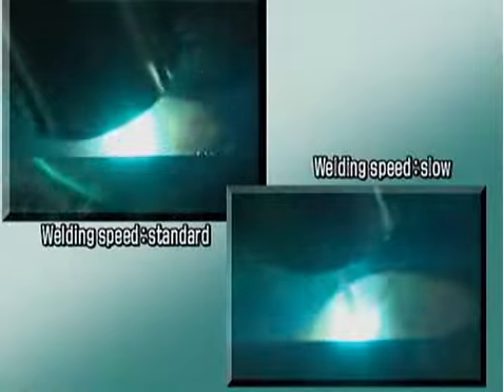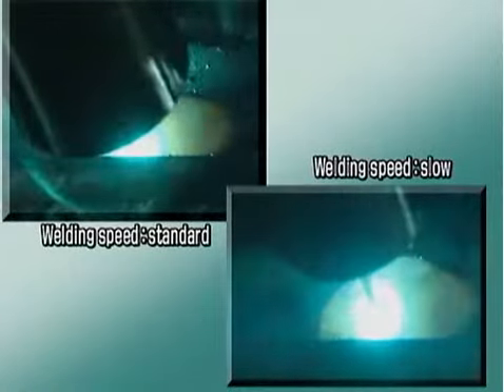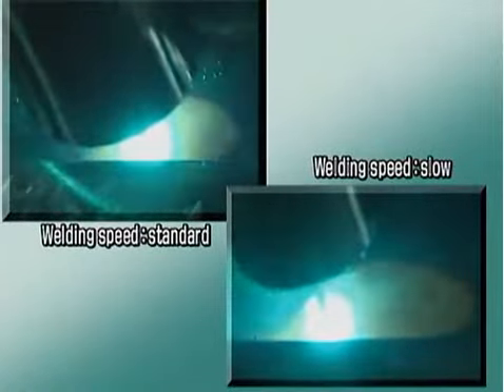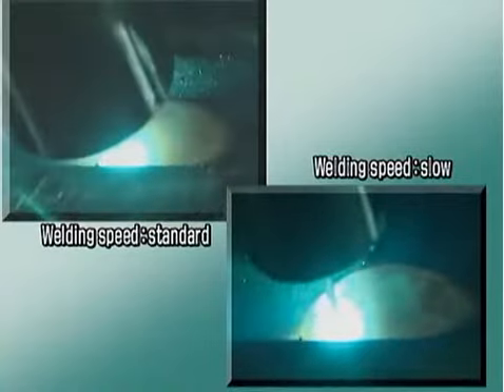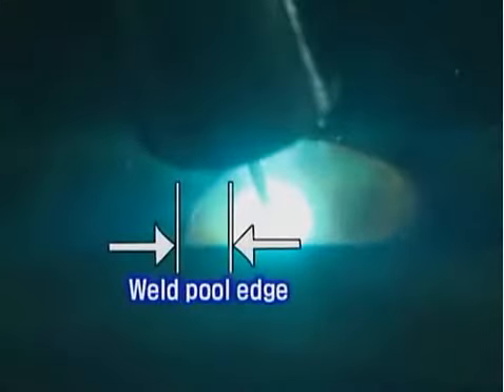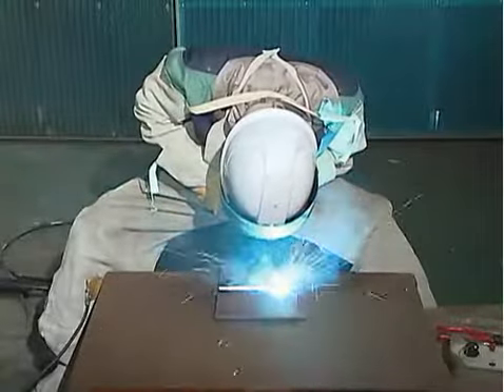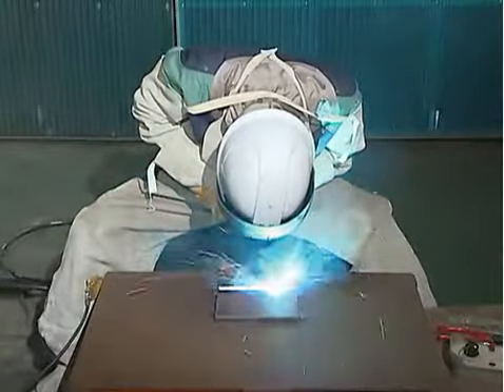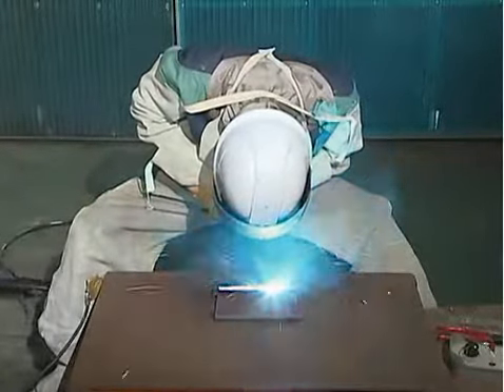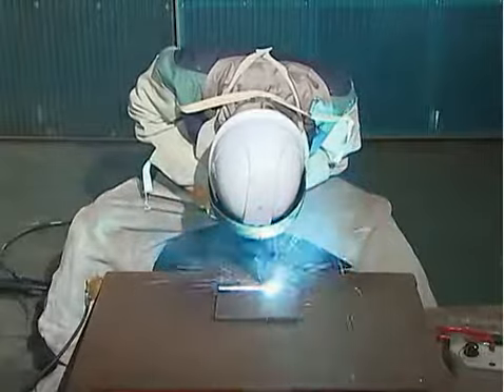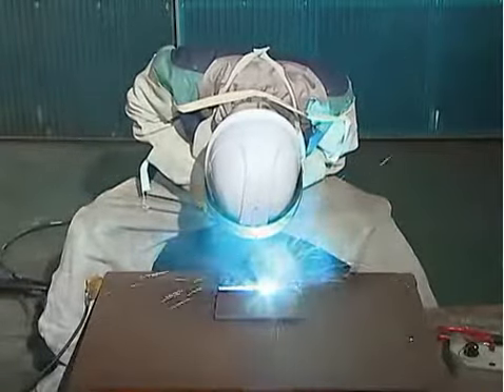Also be careful about your welding speed. If it's too slow, the edge of the weld pool builds up and the weld pool extends ahead of the wire, resulting in shallow penetration. While welding, keep a close eye on the shape of the weld pool and make sure there is no deviation to one side, that the bead stays straight and doesn't build too high, or that the bead end does not sink.